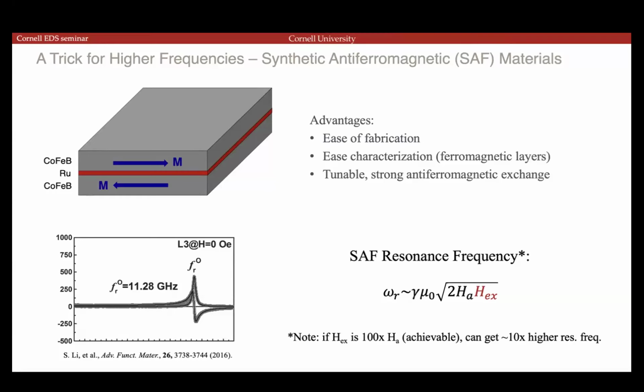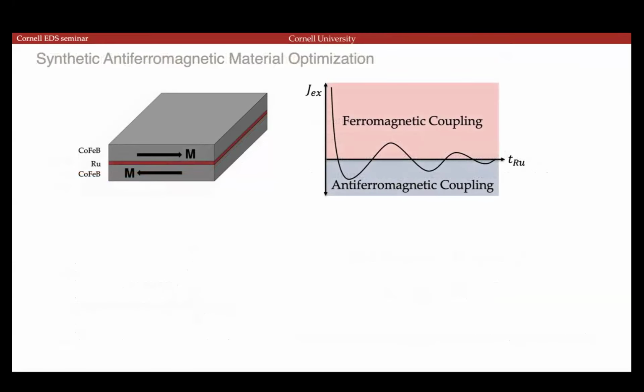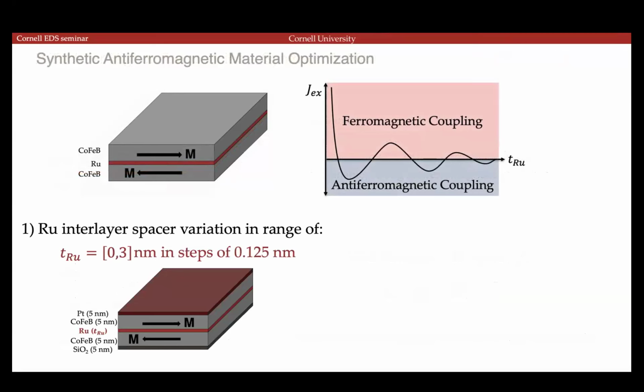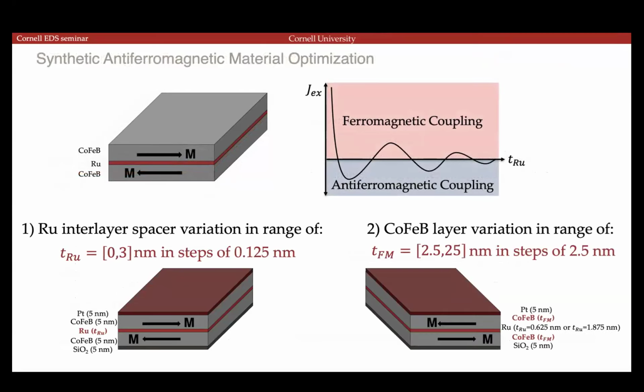In our case, we did this optimization by varying both the ruthenium thickness as well as the cobalt iron boron thickness. So if the magnetic material also grows, then the effect of the interface on that magnetic material is reduced. So there's a certain trade-off that happens as a function of magnetic material thickness and ruthenium interlayers, basically.